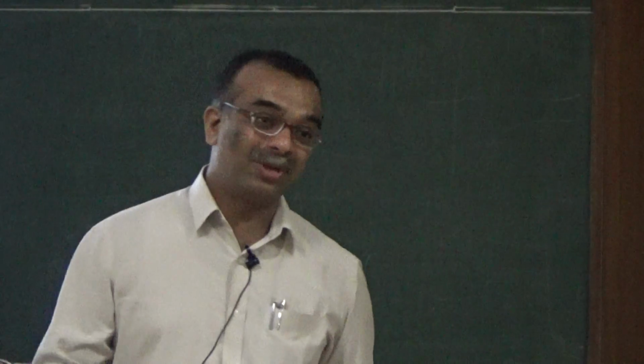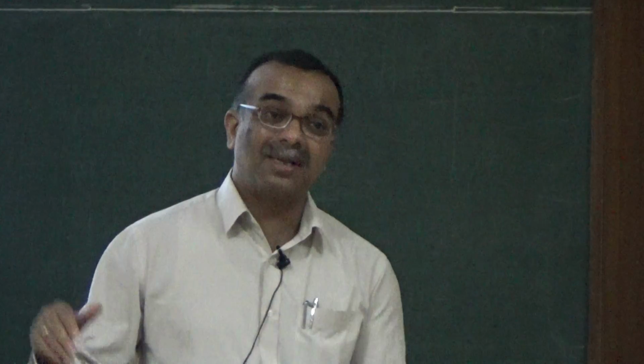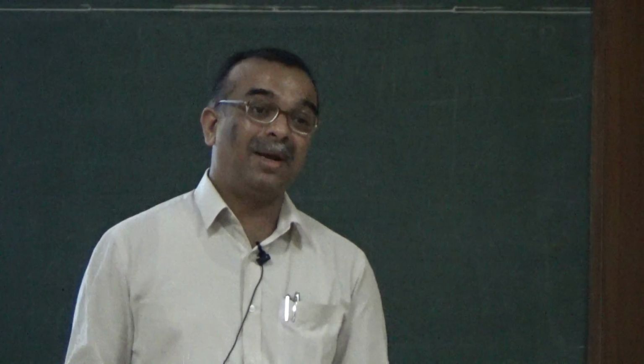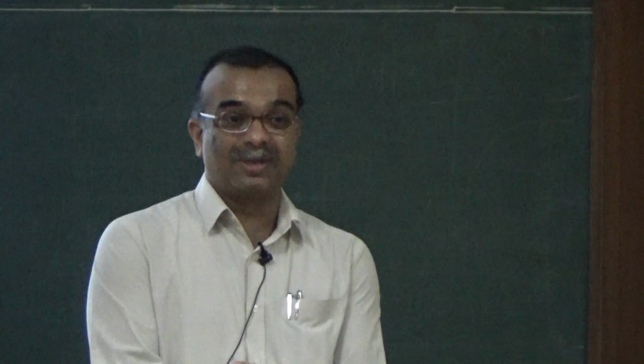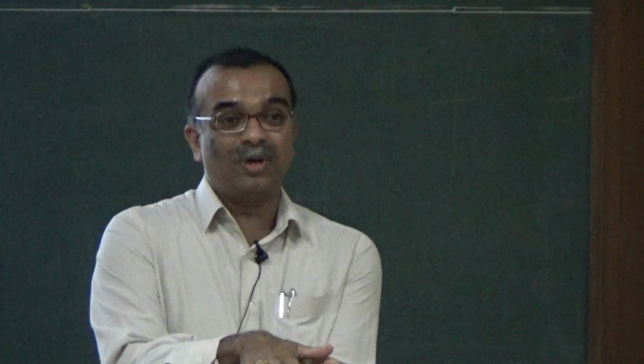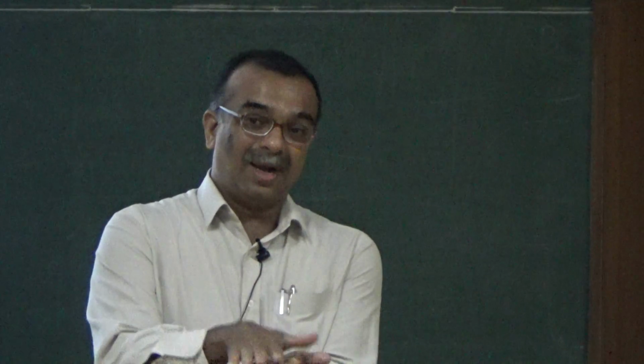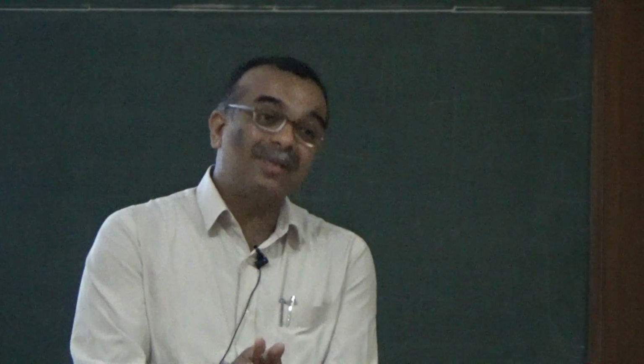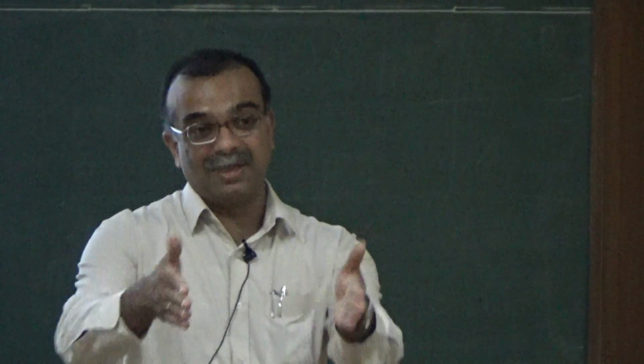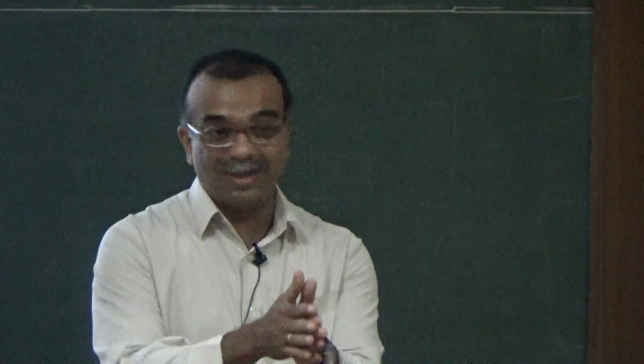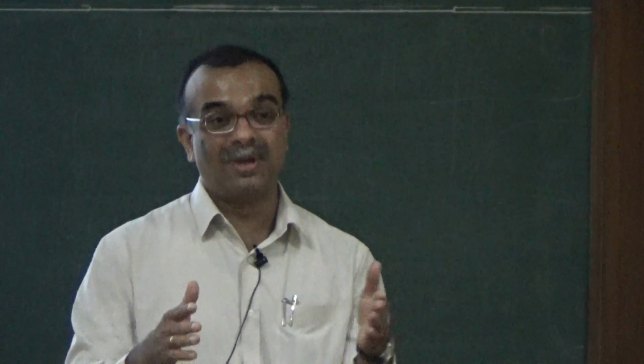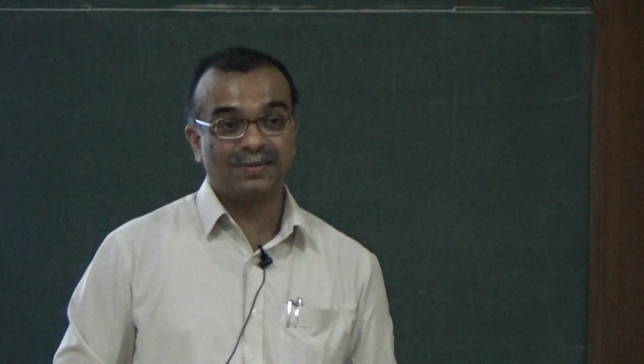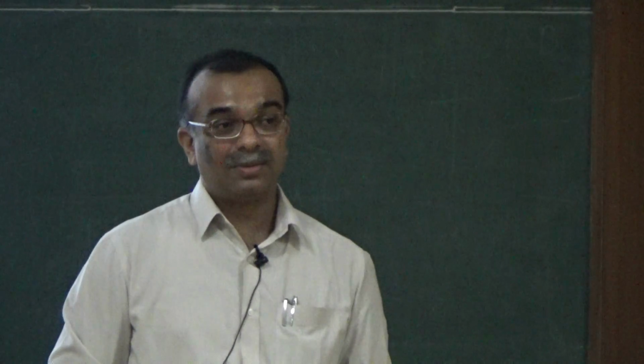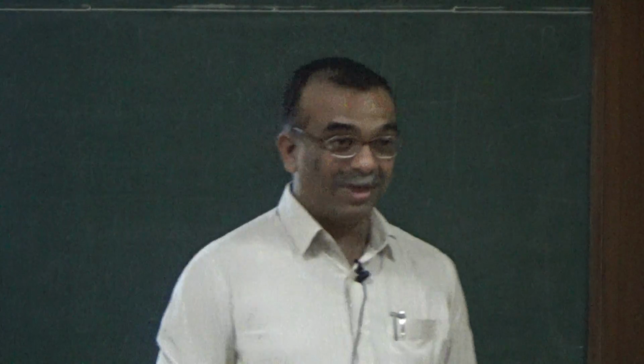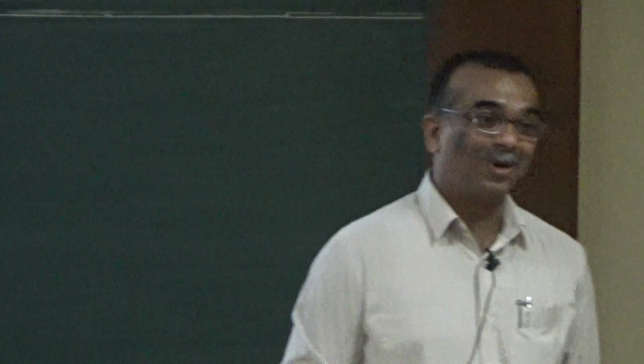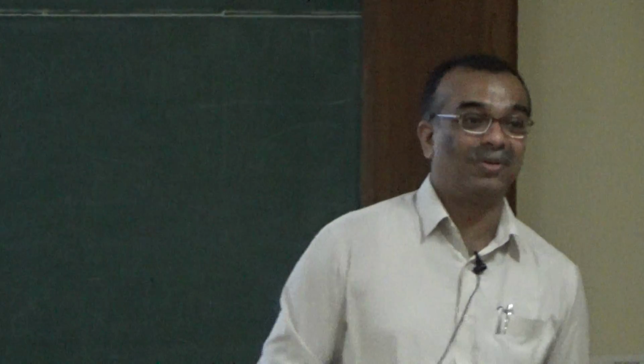Now, Arindam Ghosh's group in IISc has stabilized this form by what is called heterostructure growth. They deposited MoS2 on boron nitride, and that seems to stabilize the 1T structure, at least in sizable forms, not in the entire sample of MoS2, but notable size. In 1T, ferroelectricity is yet to be observed. Our prediction is yes, it should be ferroelectric.